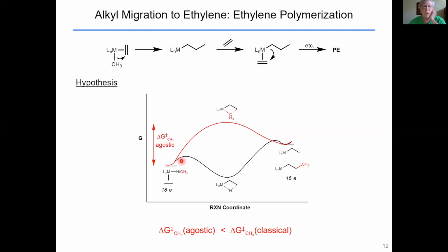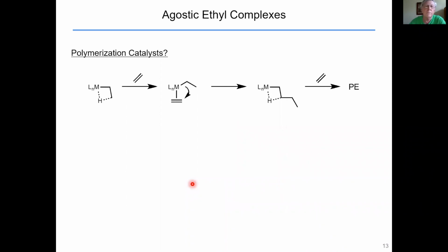And so that's illustrated here. Here's the most stable form of the agostic species. Then the barrier should be a lot lower relative to one in which the hydride is classical. And so we propose that if we generate an agostic ethyl species and expose it to ethylene, we should displace the CH interaction to make the alkyl olefin complex. This should undergo migratory insertion to generate a new agostic species with a butyl chain that can bind ethylene and so on, and we should be able to generate polyethylene.